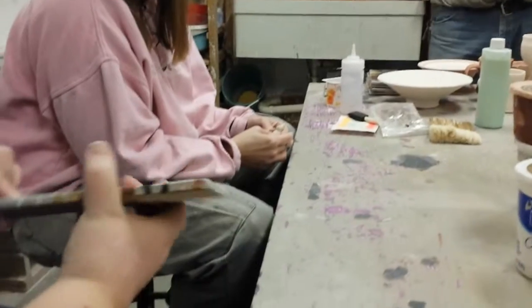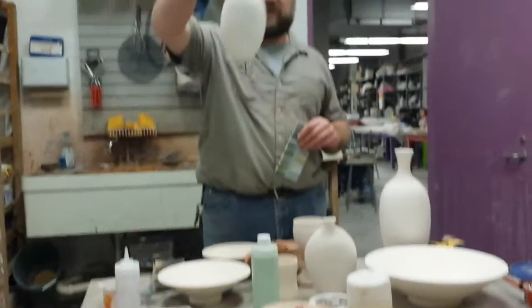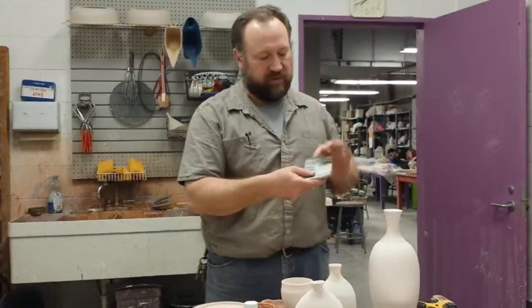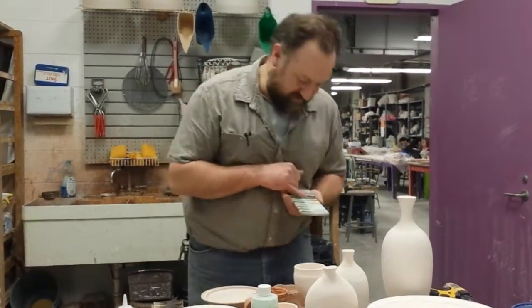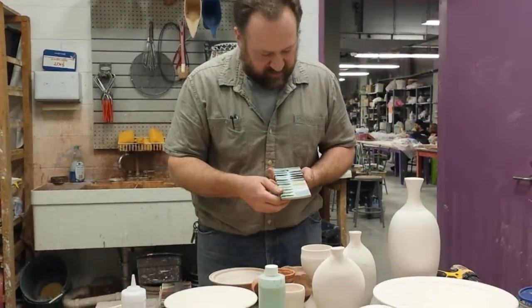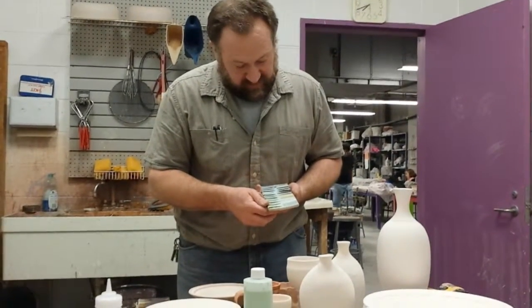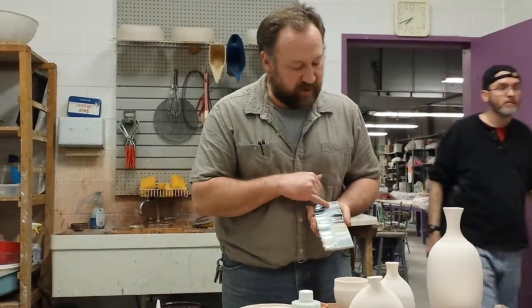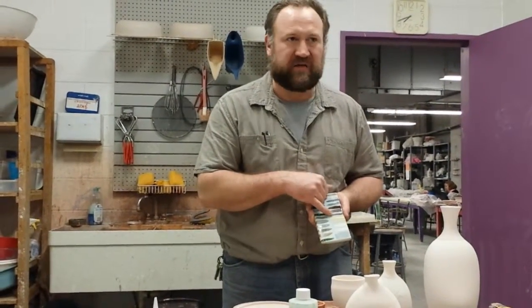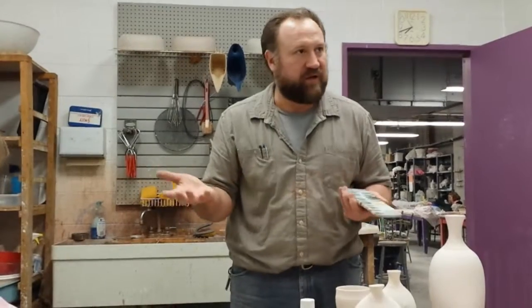The clear actually stayed pretty true. So here on this bottle, I've got light green slip. I would definitely reference this so I don't lose that greenness — if I were to glaze the whole thing in tomato red, not much green is going to be left. So I would definitely pick something that should allow that green to come through. In this situation there really aren't many choices — the two celadons would work okay, the carbon trap might even be okay. The copper red reading is probably not real accurate because it's hard to get the copper red as thick as it needs to be in that little strip, and a real thin copper red might let it shine through, but that's not going to get you red.